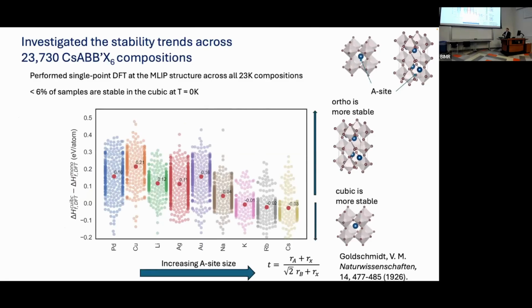So for example, we can take the potential and apply it to the whole space. In this case, we've taken a subset of just the cesium A, B, B prime X6s, and investigate, for example, what does it look like in terms of stability if you take one of the A site atoms and you change it. So you go from cesium to something that's smaller. So this is decreasing size of the A site. And Victor Goldschmidt, 100 years ago, published this Goldschmidt tolerance factor, which has really guided a lot of the work in trying to find stable compositions in the field.